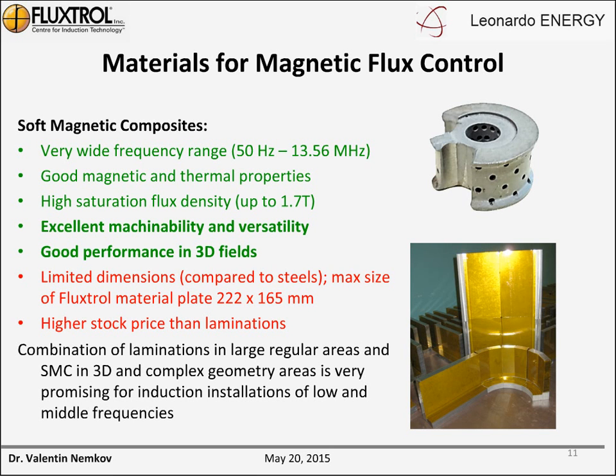Two next points are very important: excellent machinability and versatility of the material, and good performance in 3D fields. Some drawbacks: limited dimensions compared to steel, not to ferrite. The maximum size of material for Fluxtrol type, which is the largest known to us, is 222 by 165 millimeters. Higher stock price than laminations. A combination of laminations in large regular areas and soft magnetic composites in 3D and complex geometry areas is very promising for induction installations of low and middle frequencies.